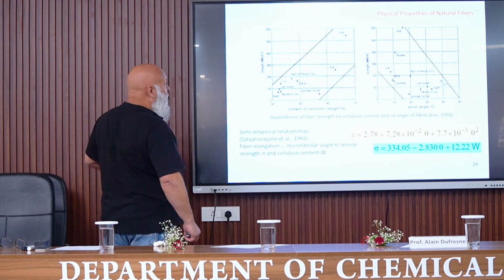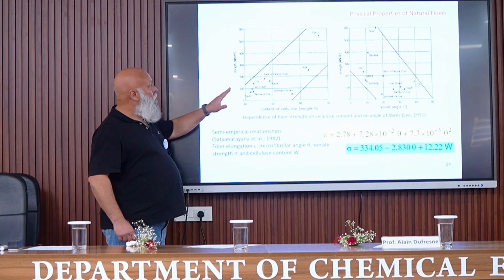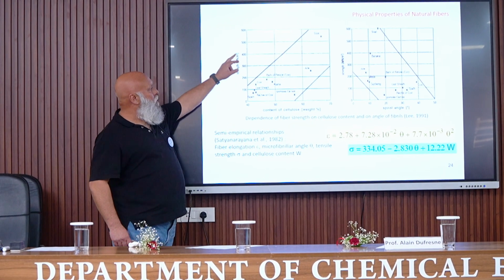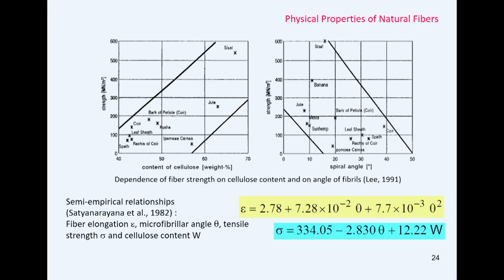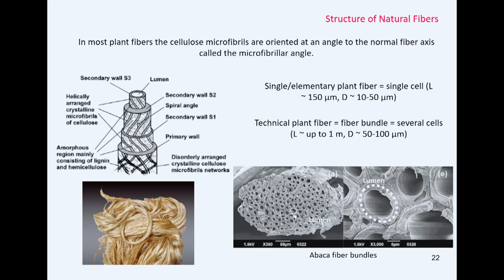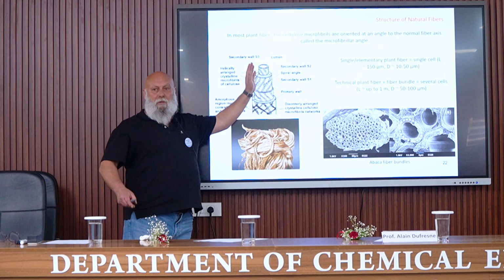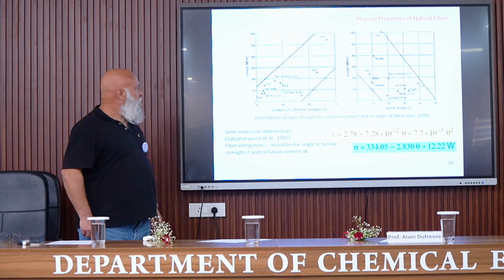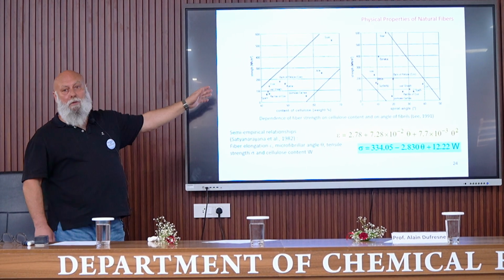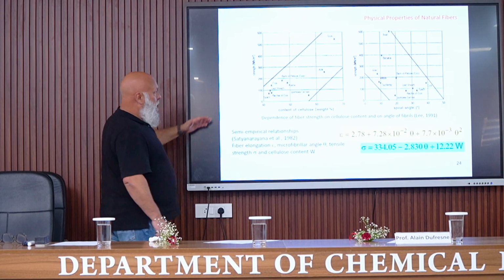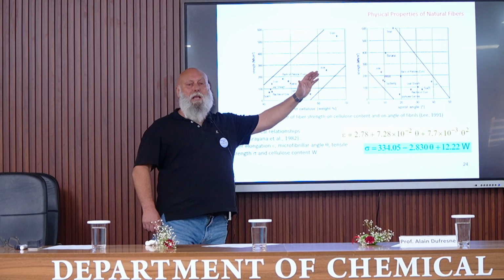You have here two graphs in which you have the evolution of the strength of the fibers as a function of cellulose content and as a function of the spiral angle. So the spiral angle is this microfibrillar angle. So it's exactly the same thing. And you can see, for different natural fibers, that there is a kind of correlation.